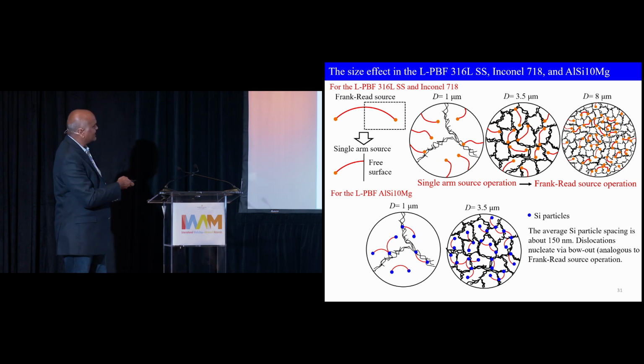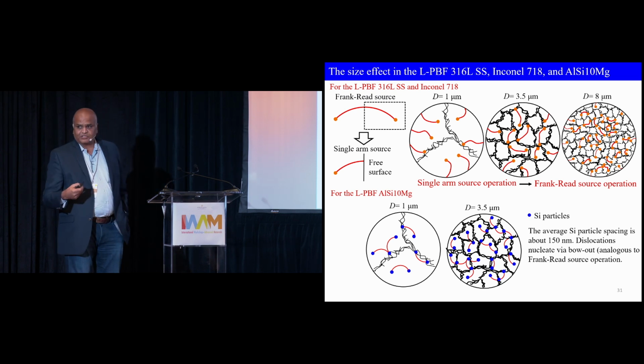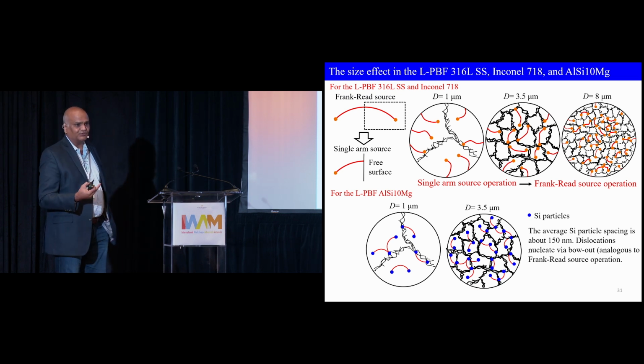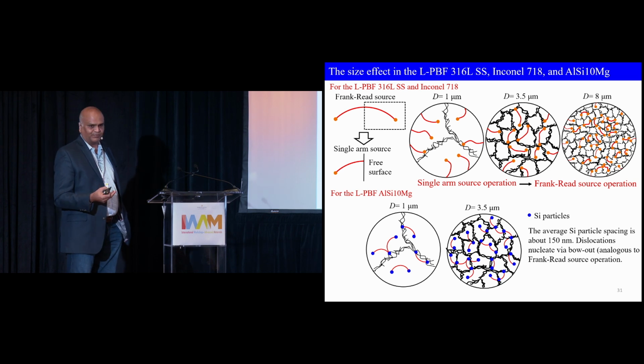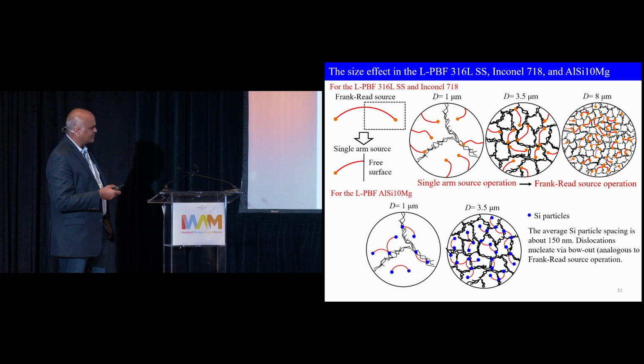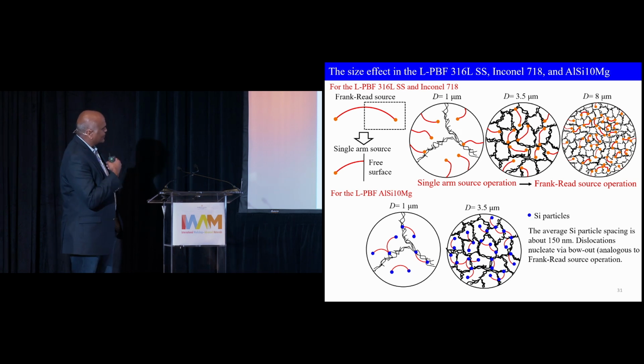In the aluminum silicon case, we actually have particles, since silicon solubility in aluminum is very, very negligible. So it all precipitates out as nanoparticles, and that's why even if you go to 1 micron, you get the bulk strength.